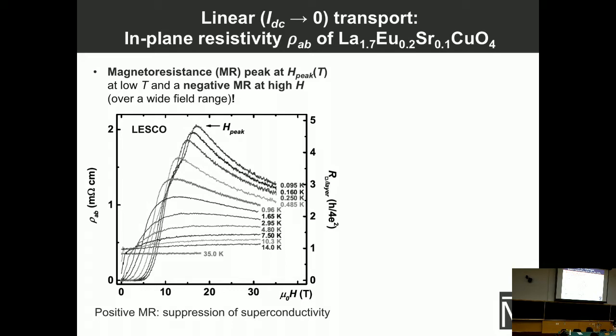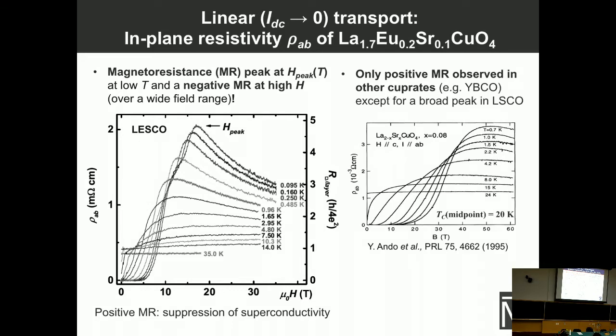People have seen only positive magnetoresistance, with the exception of this early study by Ando and Boebinger, where in LSCO, at their lowest temperature and very high fields, they observed a broad peak. This obviously represents some characteristic energy scale where something changes. We see that the position of the peak depends on the temperature, so we can track this position as a function of temperature.